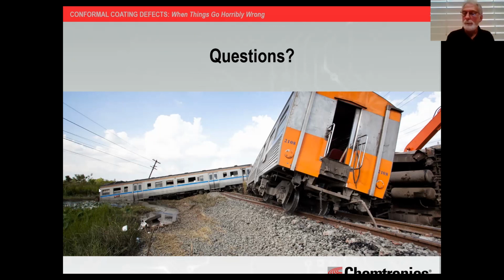Yeah, and you bring up a real good point in terms of permeability of coating. There's a misconception that commonly comes up: dirty or clean, you seal it up with conformal coating to fix it, and that's not how it works. It's a really important concept to realize that yes, you can make a board water resistant, but you're not waterproofing it with these coatings. They're semi-permeable. Some of this can get in and still continue to react with what's under that coating. So really important. So Liam, thanks for your question. Current undercoating. Okay, he clarified. So I think we've got that answered.